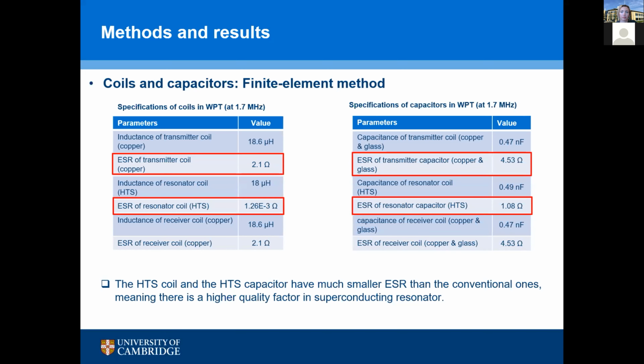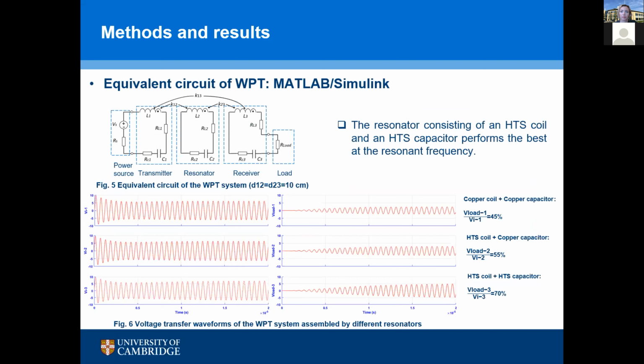The two tables show the calculated results of the related parameters. Obviously, the HTS coil and HTS capacitor have much smaller ESR than the conventional ones, meaning there is a much higher quality factor in the superconducting resonance. It is worth noting that I consulted colleagues in our division who did this kind of measurement. They also agreed these figures are quite reasonable. Next, the WPT system's equivalent circuit can be simplified as shown in the top figure. Then we put the component data we just got into this system, developed in MATLAB Simulink.